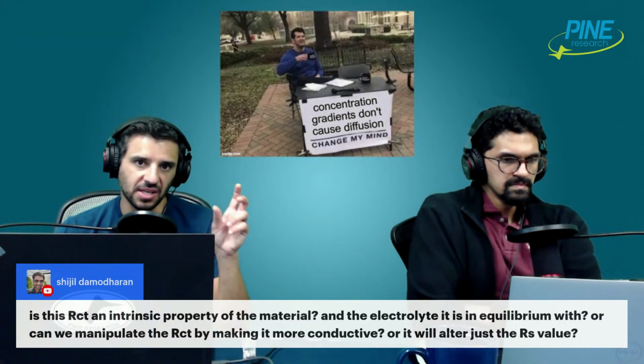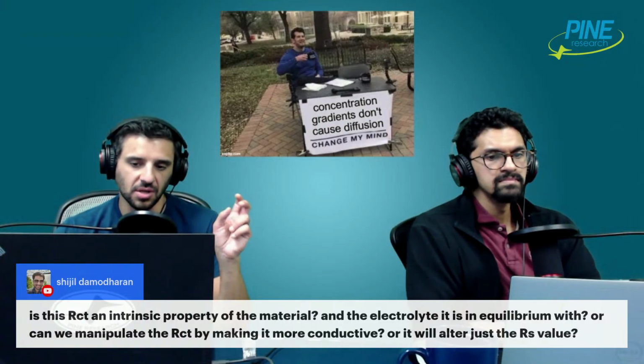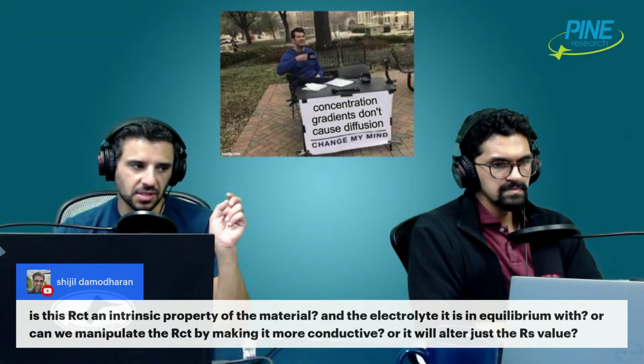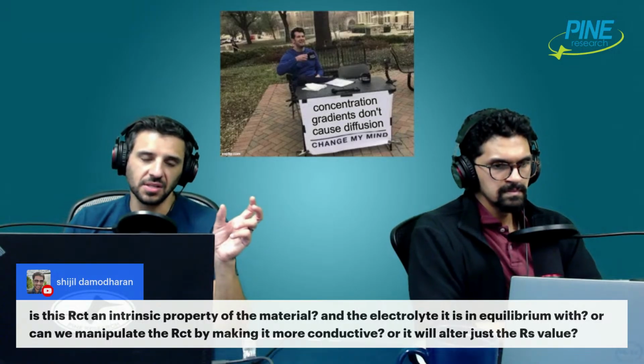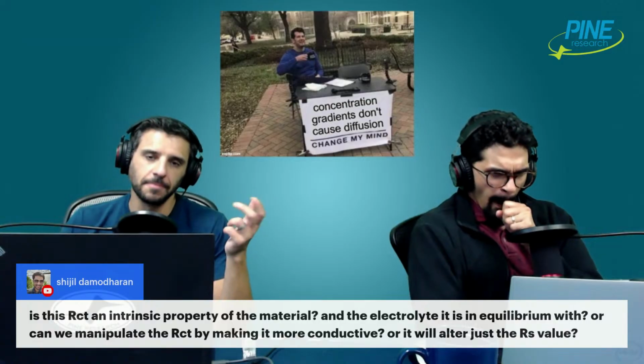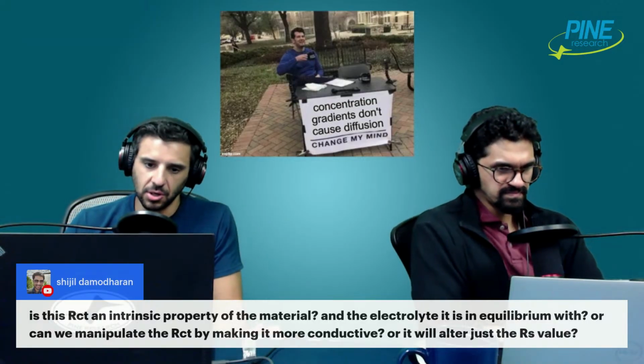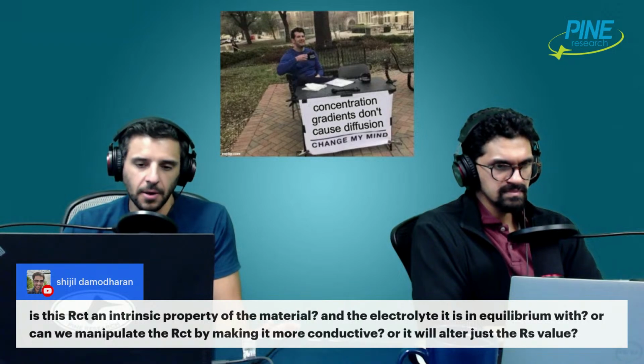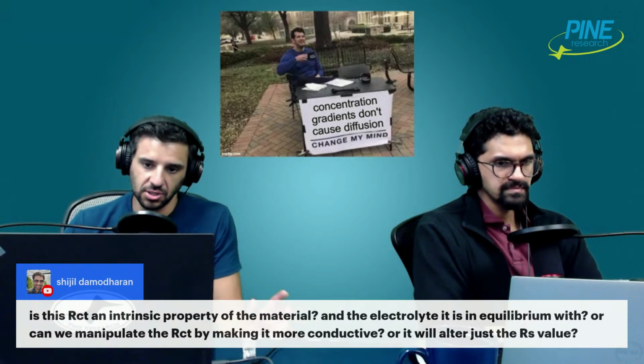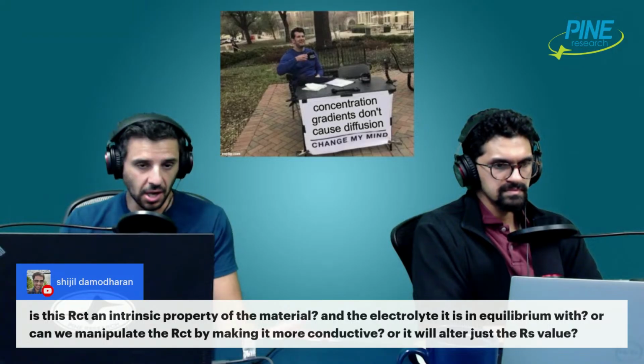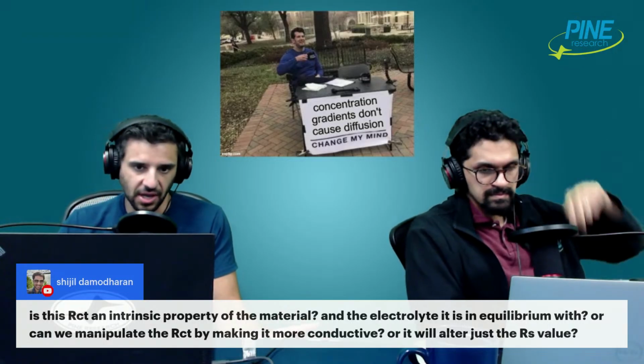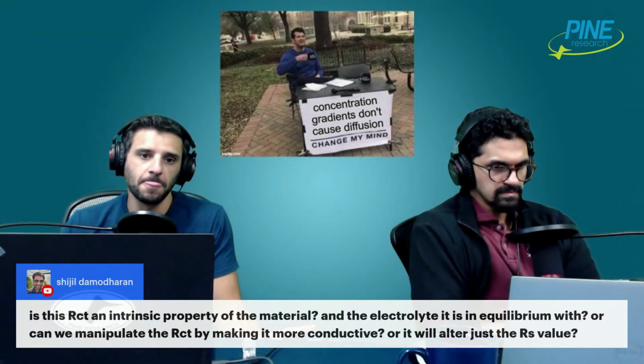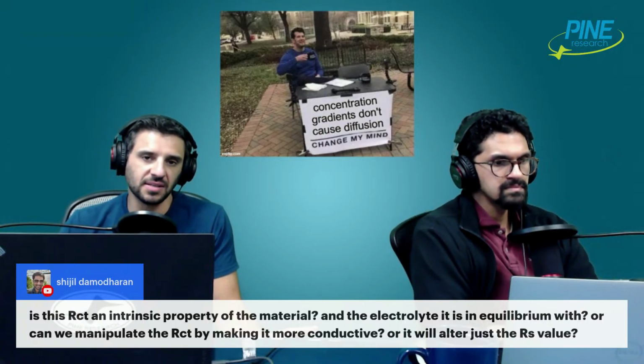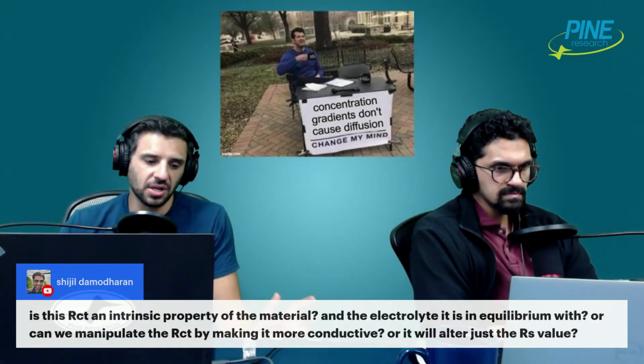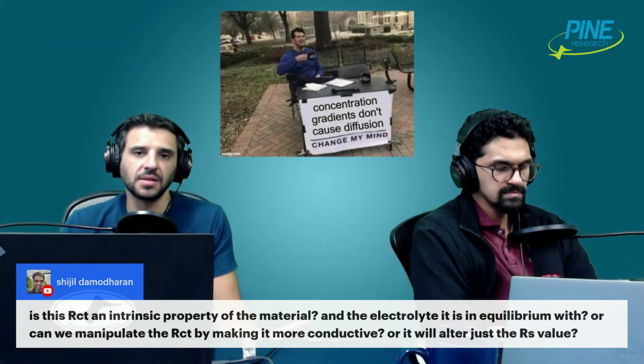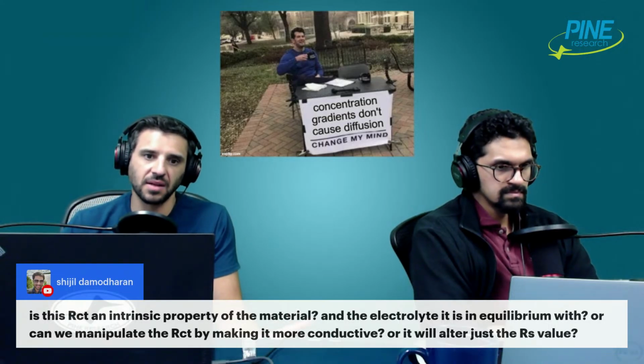And so the RCT is more closely a function of that potential. Visually, we see that with the Nyquist plot, for instance: the width of a semicircle will decrease as you increase the overpotential, usually. Because you're increasing the overpotential, you're increasing the driving force for the reaction to occur. Therefore, you are decreasing the charge transfer resistance. Now, another material or a different electrolyte can affect the RCT as well. But in almost all cases, it's the applied potential at which you're conducting your redox process that will more heavily impact your measurement of RCT.